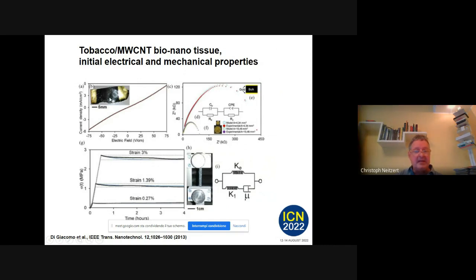Here you see the sample. Again, it looks very black. It has some transparency, nevertheless about 4% or so. It was a thick sample of 100 micrometer with gold contact, standard, big sample. And we measured first electrical characteristics. Here it's at 75 volt, 6 milliampere per centimeter square.